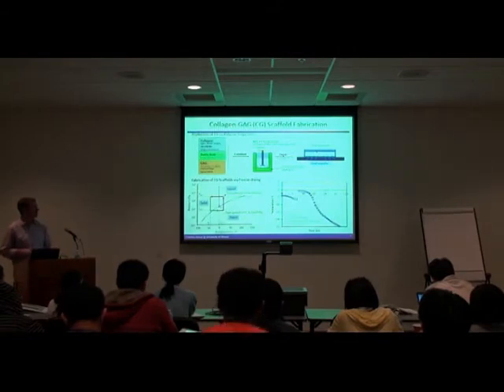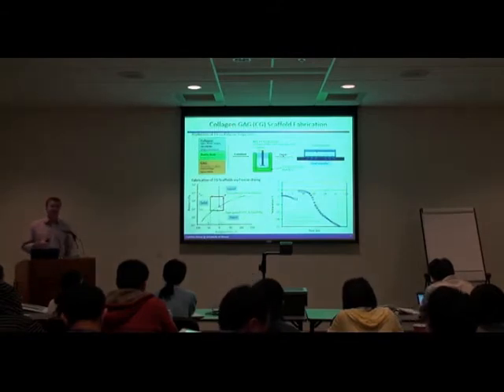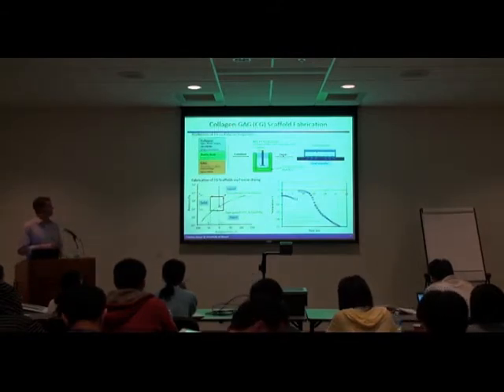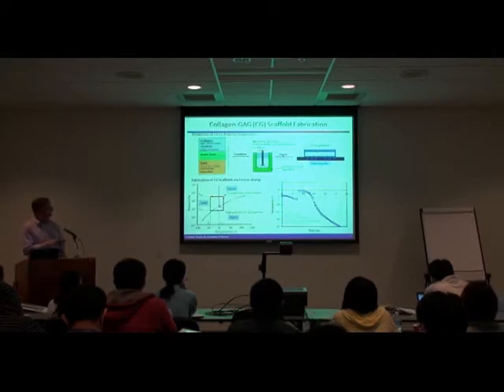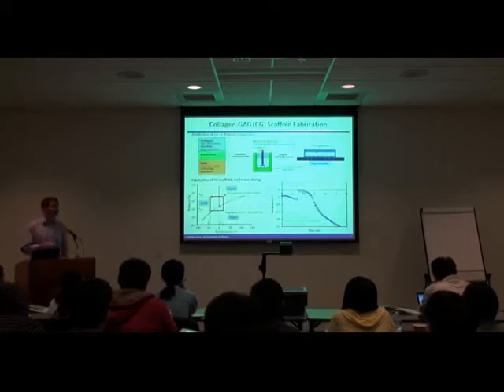So let's talk about how we make these biomaterials. As I said before, these are collagen-glycosaminoglycan, or CG, scaffolds, and they're fabricated by making an aqueous suspension of our different proteins. In this case, type 1 collagen and chondroitin 6-sulfate is our standard material we work with. We mix them together to form this aqueous suspension, and then we solidify it.